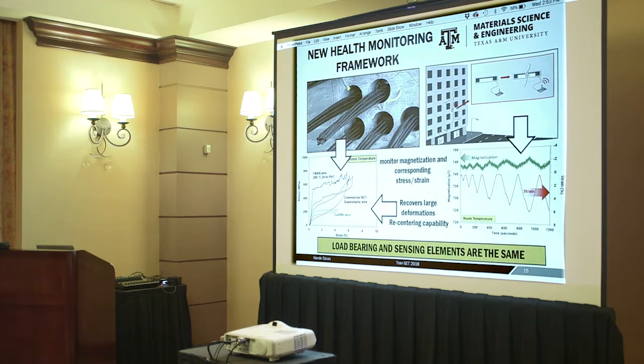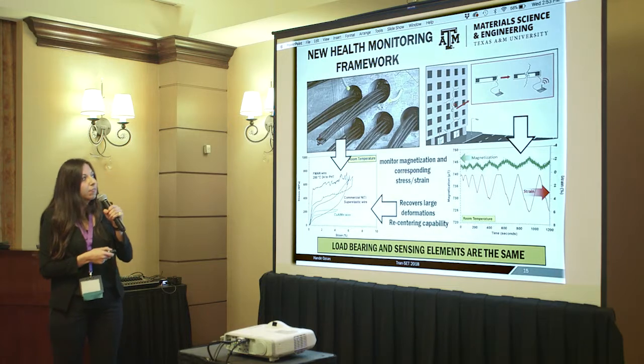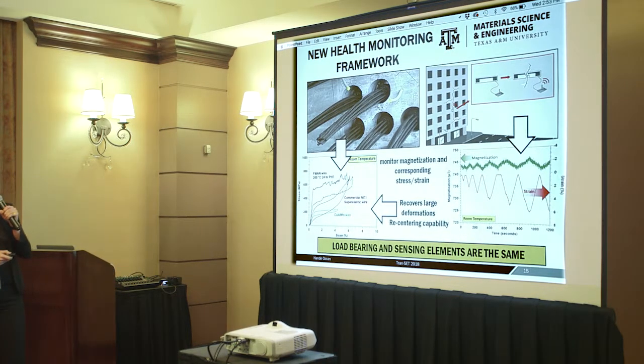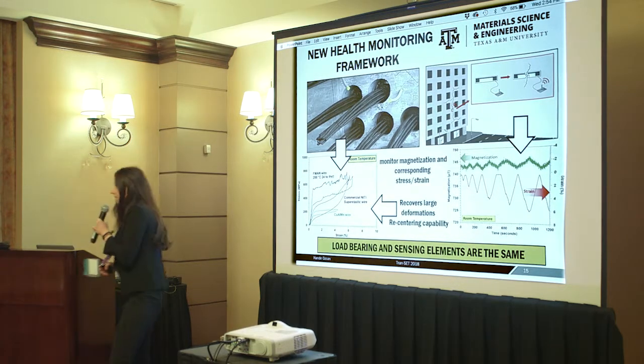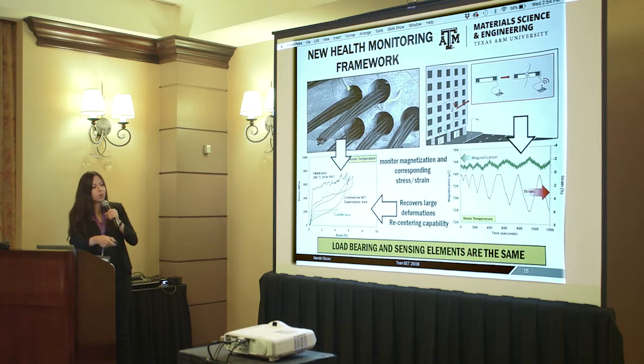Now, how can we use these two properties to solve a problem in civil engineering applications? Can we detect cracks? Yes, because imagine there is a crack in the structure. As this crack propagates, the stress state around the crack will change, and that will induce a transformation in the iron-based shape memory alloy. That also changes its magnetization, which we can detect. So we are proposing a new health monitoring framework in civil engineering where, if we use the iron-based shape memory alloy, we can detect the cracks easily. The most important thing here is that our load bearing and sensing elements are the same.